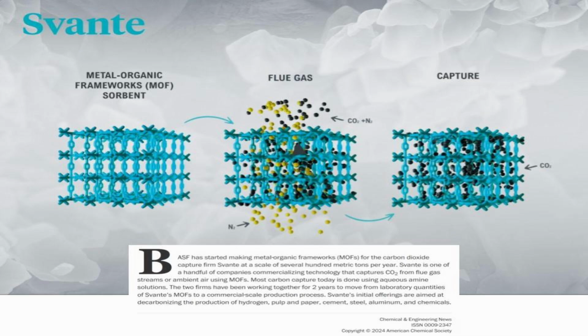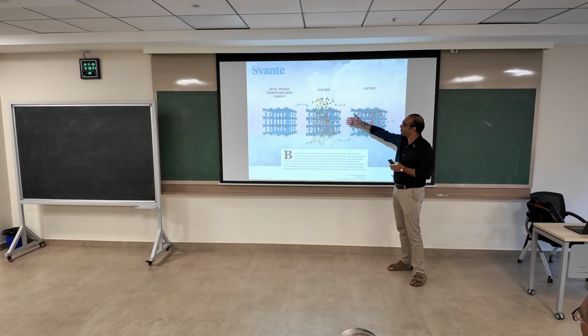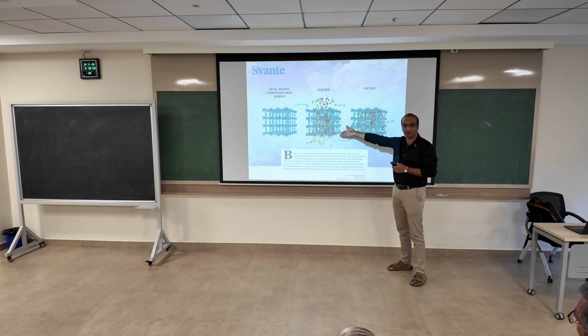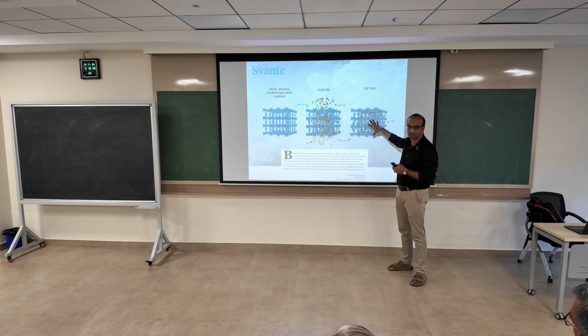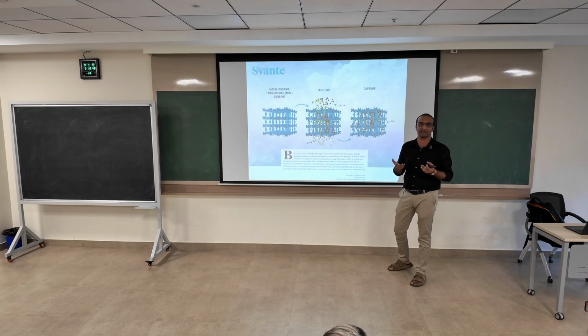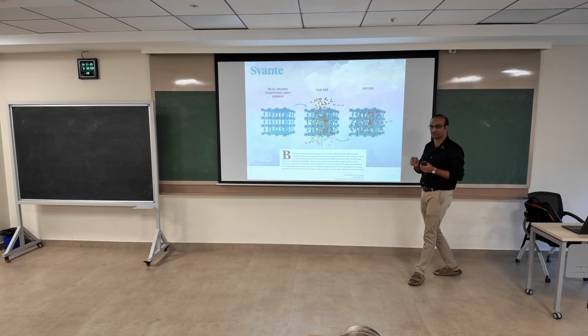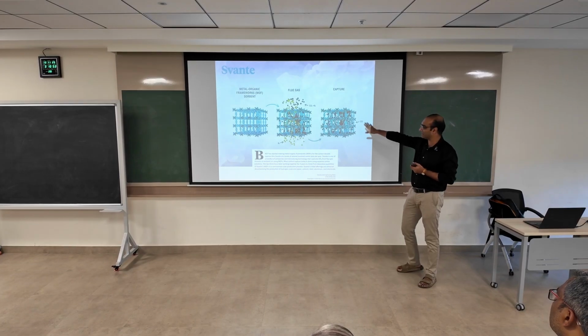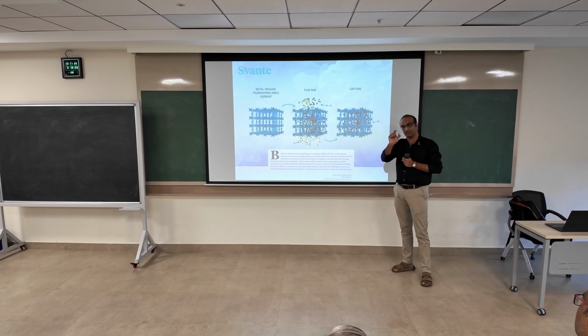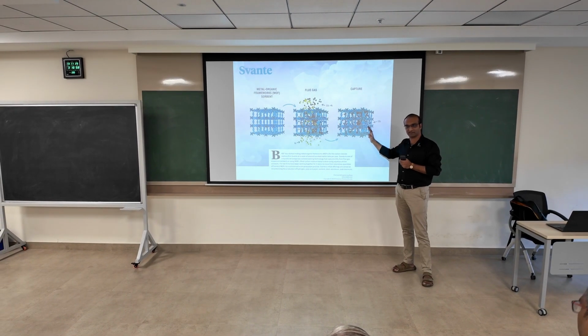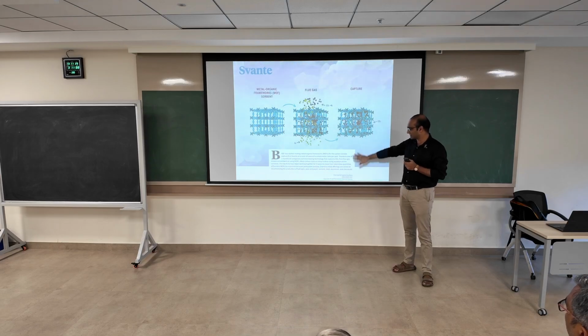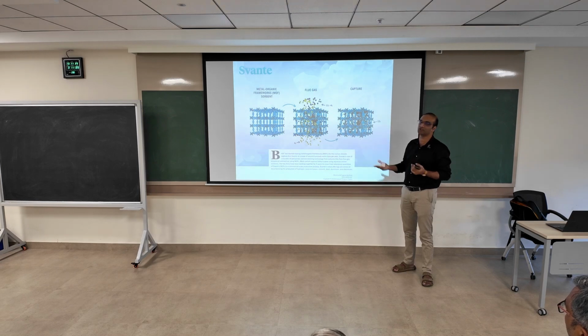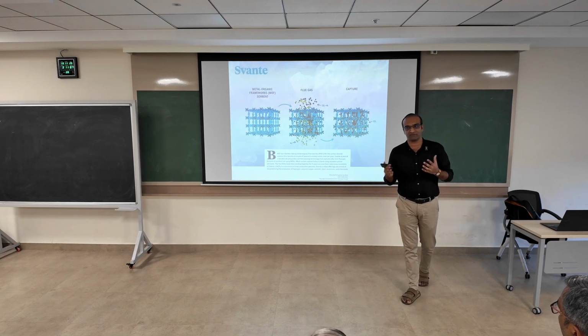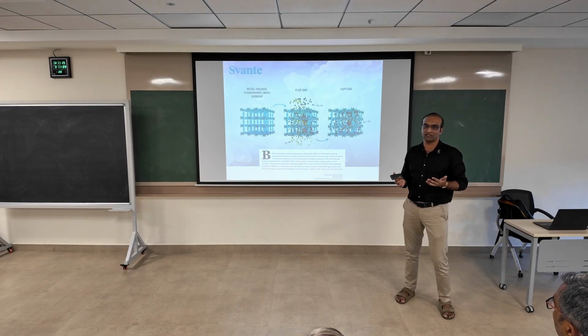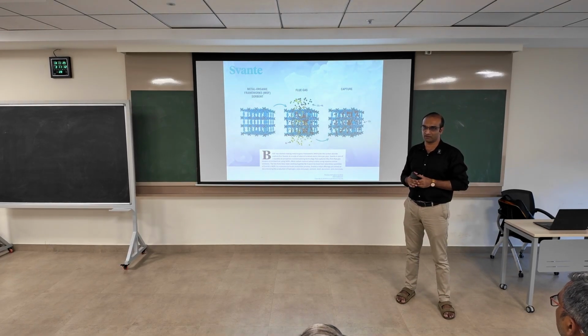So what happens essentially is you have your flue gas coming in, you have your CO2 and the N2 going into the MOF. The CO2 stays. Okay, it stays there unless you want to heat it at a low temperature, just 100 degrees Celsius. It'll release it. And this MOF is stable in that steam and CO2 mixture even at 150 degrees Celsius. Okay, so this is the first MOF that has actually been commercialized, and it's probably going to be used in any of these facilities where you have a flue gas facility, and they want to bring down the amount of emissions they put out into the atmosphere.